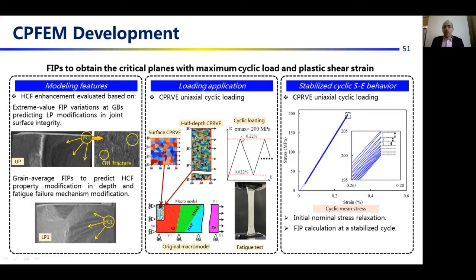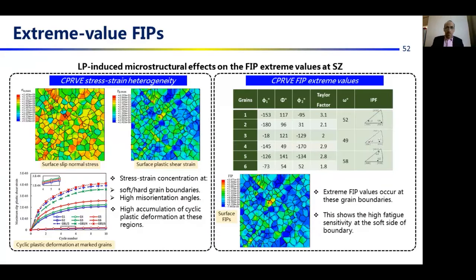simulated based on the experiment with the strain controlled regime with the highest stress of 200 megapascal and the stress ratio of 0.1 corresponding to the experimental HCF test. And the stabilized stress strain cyclic loading is considered for the calculation of FIP parameters, which represents the rest of the high cycle fatigue loading after the initial relaxation of the mean stress.